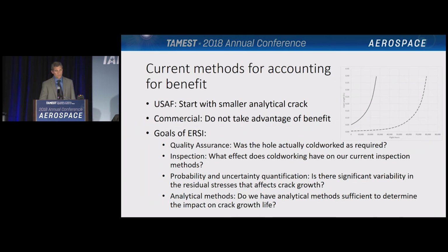So we know that cold working holes causes fatigue cracks to grow much more slowly, but we schedule maintenance based on the expected crack growth. So in order to take advantage of that benefit in our maintenance processes, we have to incorporate cold working into our analyses somehow. So how's that done currently? Well, Air Force guidance on incorporating cold working into analysis, which was written over 30 years ago, is to start your crack growth analysis with a smaller crack size and make no other changes to the analysis. This does increase the analytical life of the crack, as shown in the plot on the right, but it doesn't incorporate the physics of the residual stresses at all. We know we can do a lot better than that with the capabilities we have now.